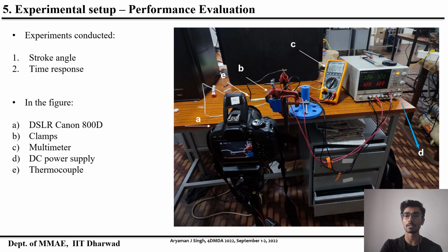This was our experimental setup. We conducted experiments to measure stroke angle and the time response of the actuator. The equipment used can be seen in the figure. The DSLR camera was used to take pictures and record the actuator in action. Clamps were used in the experimental setup to fix the actuator at one end while keeping the other end free to bend. A thermocouple was used to keep track of the temperature of the SMA wire, and finally a DC power supply was used for joule heating.